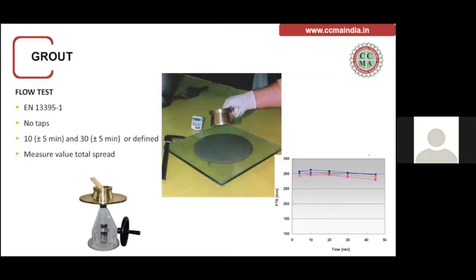Very small test at site which can be done with the cup cone, wherein at 10-minute to 30-minute time we can see the result, how the spread is happening. You can see the graph here. At 10-minute it should give 295 to 300 or slightly higher than 300. This cup cone has a size of: the top is 50, the bottom is 100 and the height is 70. So the cup cone is filled